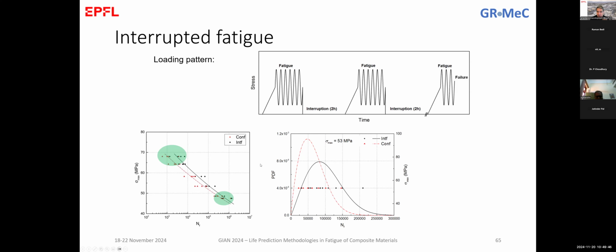We also did a similar analysis as we did in the previous work. We tried to fit the specimens of the two curves with a Weibull distribution. We've seen that it fits well. This is the analysis for the specimens at 53, so at this stress level here, where we had again more than 10 specimens to compare. And there you can see that the behavior is improved quite significantly. From 70,000 cycles, we went to 112,000 cycles. This is the average of the median, the median curve.